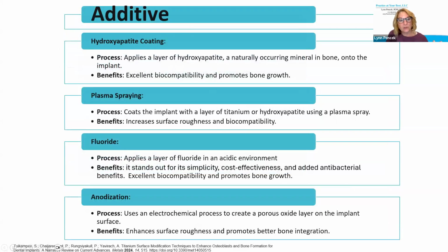Besides machining, we can also work with additives. So instead of removing surface texture, we can give additional chemistry to the surface texture, one of which is using hydroxyapatite. And the hydroxyapatite will naturally encourage the mineralization of the bone to the implant. It's got great biocompatibility and promotes bone growth. Plasma spraying creates that implant layer of the titanium and the hydroxyapatite.